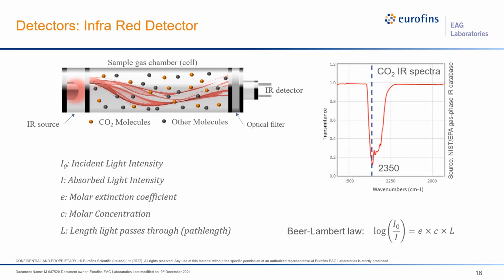Now let's talk about detection methods. The first method is using an infrared detector. This type of detector works on the principle of light absorption. An IR emission from an infrared source passes through a sample gas chamber. Based on the presence of gases, specific absorption takes place. The absorption is a function of the vibration energy of that gas molecule. For example, in the case of CO2 molecules, the absorption would occur at wave number 2350.